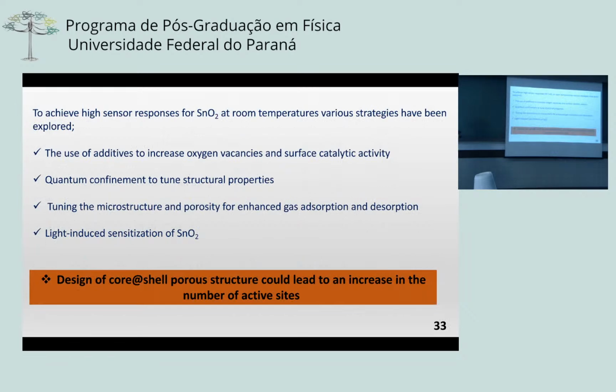So to achieve high sensor responses, there are various approaches that people have used in literature. One of them has been to use metal additives onto the tin oxide to increase the oxygen vacancies and also the surface catalytic activity. Also quantum confinement, making the particles very, very small so that you can tune the structural properties, tuning the microstructure and porosity. And the last one is light-induced sensitization. Now, looking into the microstructure and porosity and quantum confinement, can we use the templating approach, using a core shell structure, to lead to an increased number of active sites and perhaps detect carbon monoxide at room temperature?